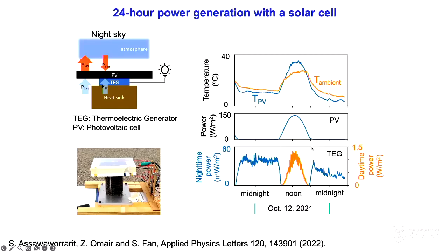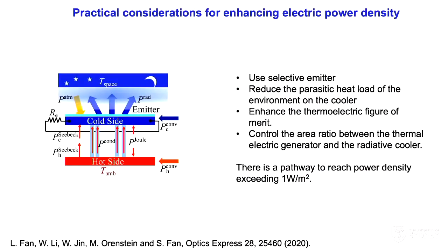The amount of power that we see in these experiments is relatively modest. As you can see here, in the silicon photovoltaic cell experiment, we have electricity generation of about 50 milliwatt per meter square. There is, in fact, practical consideration for further enhancing electric power density. And so in a theoretical paper, my student Ling Fan looked at some of these considerations. For example, on the optical side, using a selective emitter; on the thermal side, reducing the parasitic heat flow; and also, very importantly, controlling the area ratio of the radiator cooler to the area of the thermoelectric generator for better impedance matching. And she showed in the theory that there's a pathway to reach power density exceeding 1 watt per meter square.